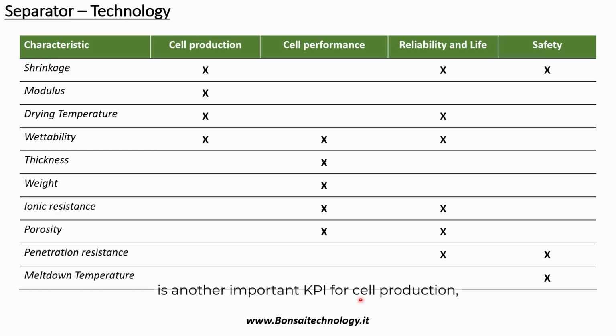The drying temperature is another important KPI for cell production, even for the reliability and life, because if the separator cannot be dry at high temperature, this creates some shrinkage. Maybe this trigger the shutdown effect, and even can create a degradation of the separator itself. So since the separator should be dry for the cell manufacturing, it's important to consider the drying temperature with the characteristic temperatures of separator. Then we move to wettability.